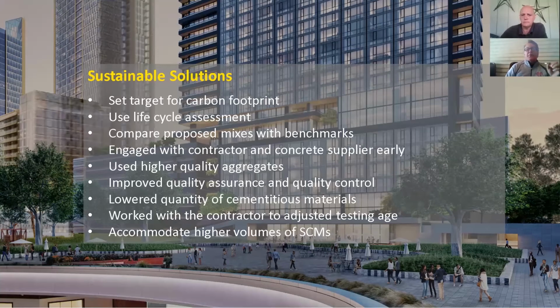Again, we cannot stress enough the importance of early communications and engagement with the contractor and the concrete supplier. Early engagement also helped tighten up the mix designs, where the single challenge of the aggregate being used, moving to an imported and high quality aggregate, improved quality control and reduced variation in the mix performance, allowing the same specified compressive strength reliability to be achieved with a lower quantity of cementitious material. The structural engineer worked with the contractor to determine where faster strength gain was really needed and adjusted testing age accordingly to accommodate the higher volumes of SCMs.